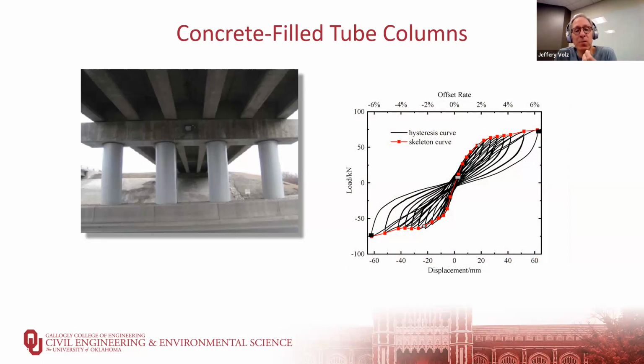Now, it's not just that we keep that load deflection from degrading. We want basically as big an area within that hysteresis loop as possible, because that is energy absorption during a dynamic loading effect. And the more energy you absorb, the lower the resultant forces on the structure and the more durable it is in terms of strength. One of the problems, though, with these types of columns is we have to protect the steel from corrosion.